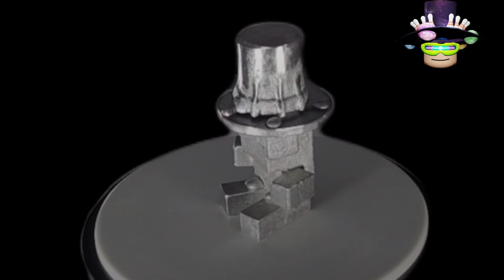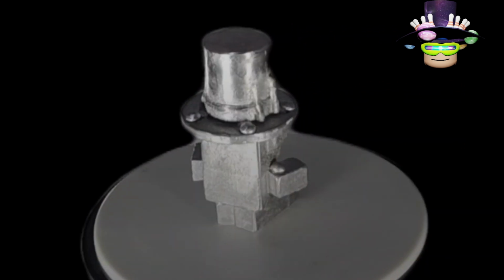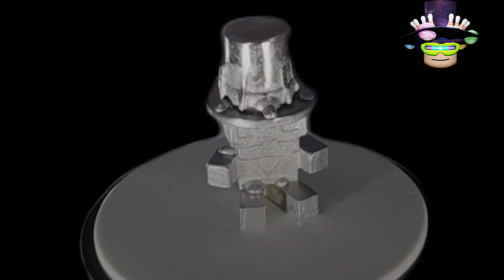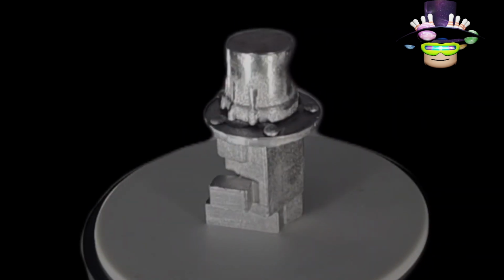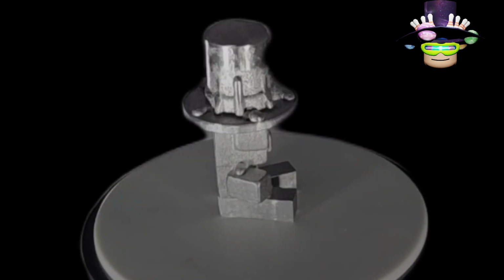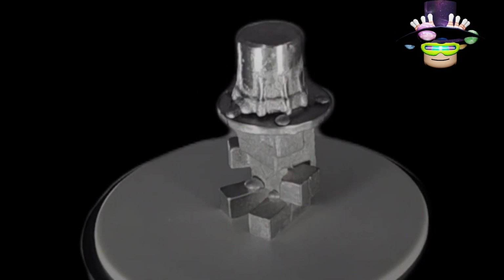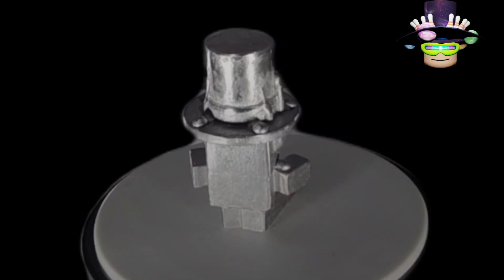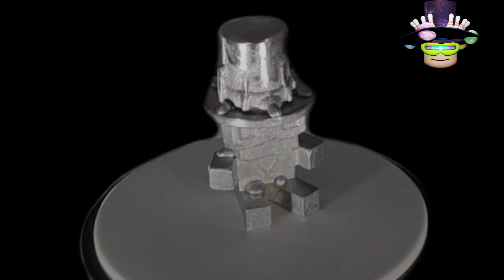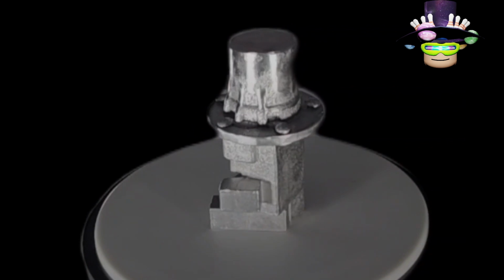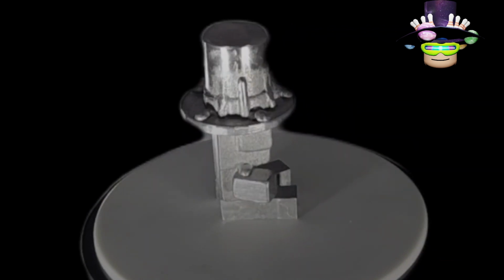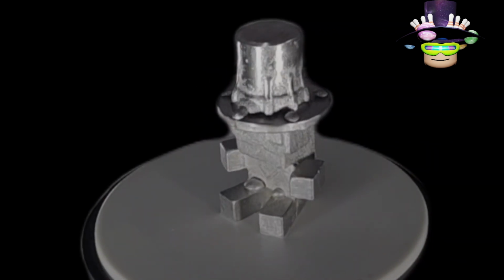Let's take a quick moment to look at the aluminum cast. Over at the top, you can see the remnants of some of the pins. This is most likely caused by air getting trapped during the aluminum pour. Another comment to add is on the right shoulder and the legs, we could see little beads of aluminum. This is most likely from air being trapped during the plaster pour.